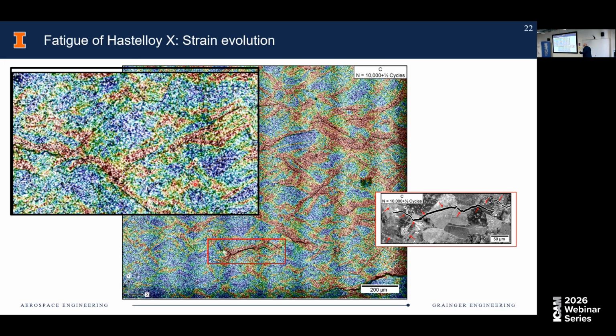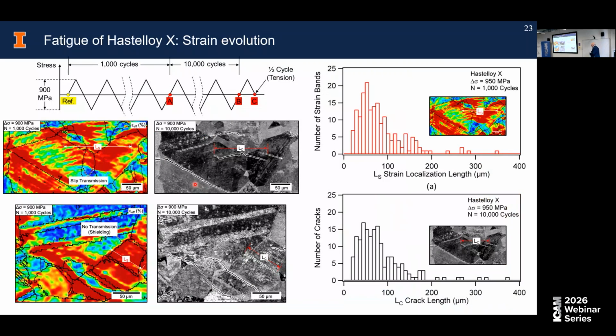That was an indication to us that these areas of strain accumulation, which seem to be determined from very early on in the fatigue loading, even from the very first few cycles, are the locations where failure would end up happening, right? But this is more than just a qualitative correlation. We also looked at quantitative correlations, and we measured what we would define in some fashion as crack length, and we just do point to point rather than following the entire crack length. And we try to correlate that with the length of measured strain at 1,000 cycles.